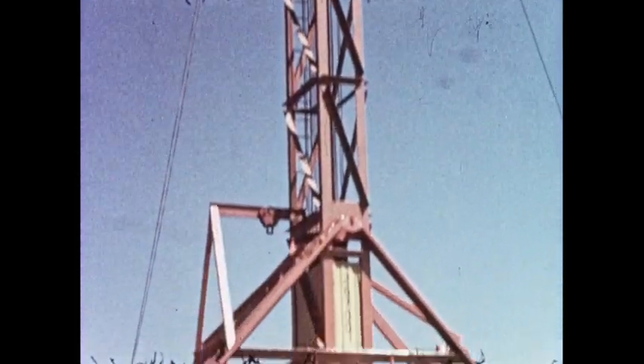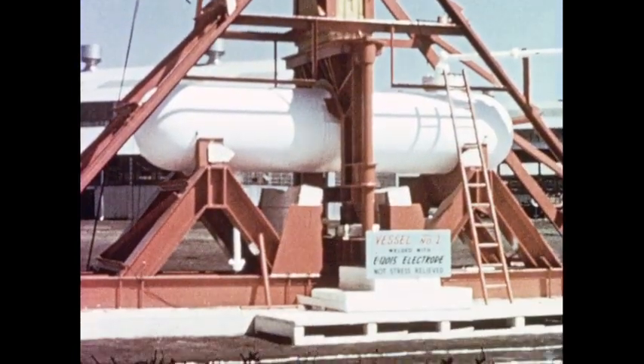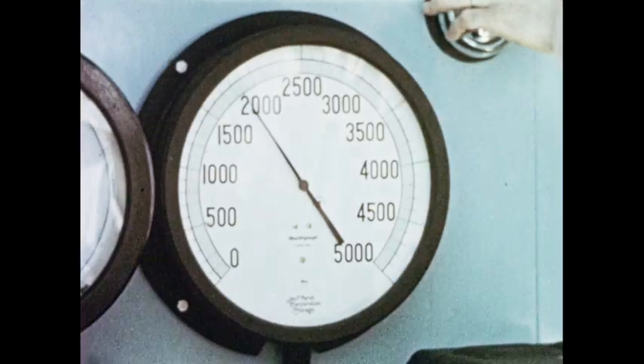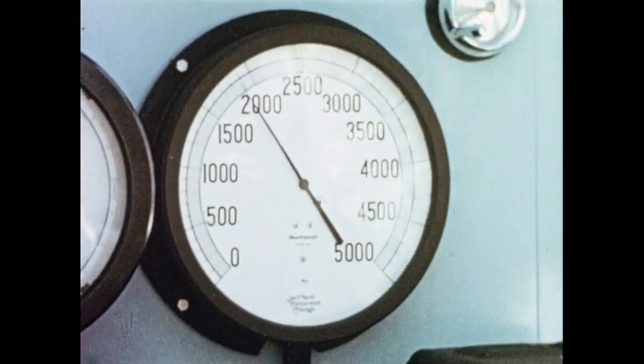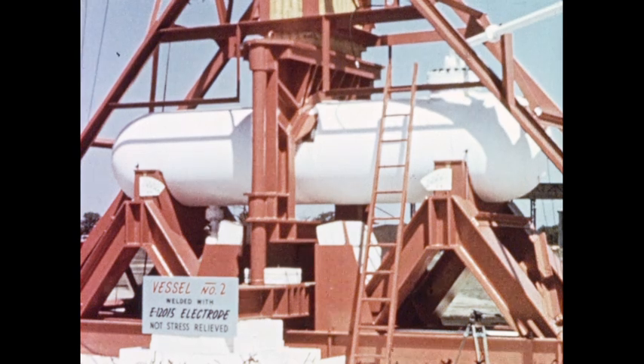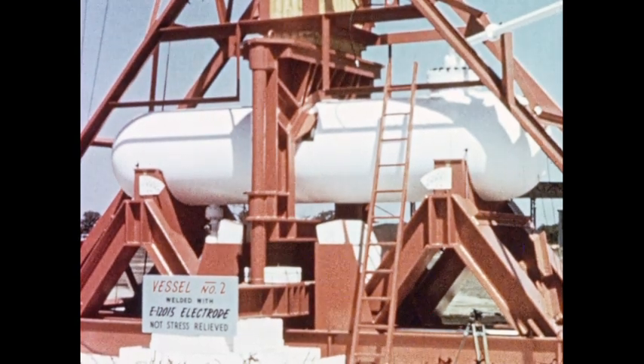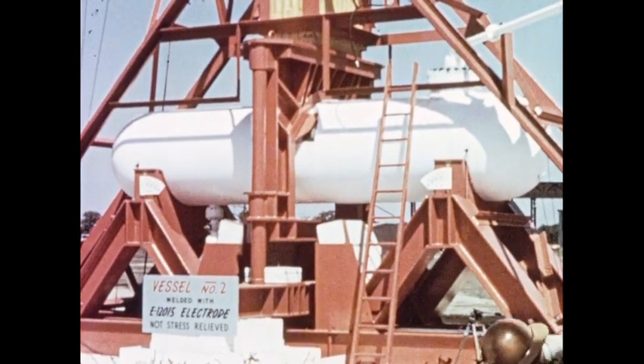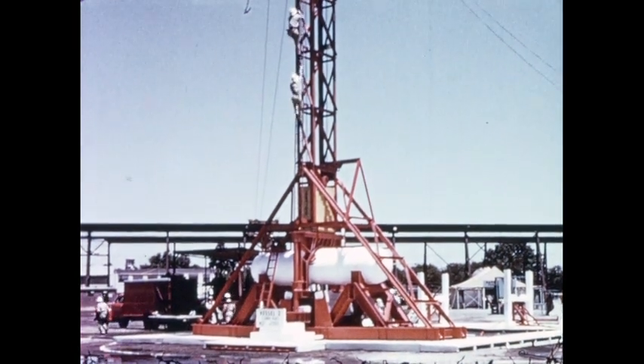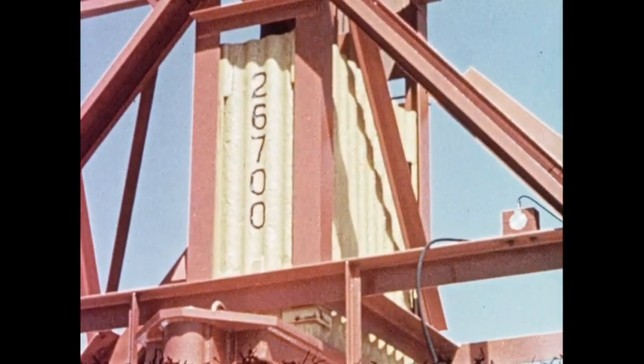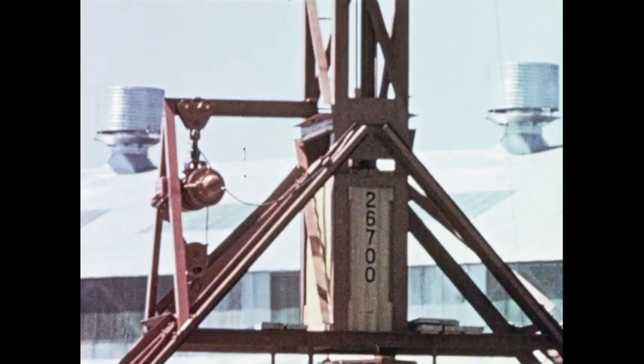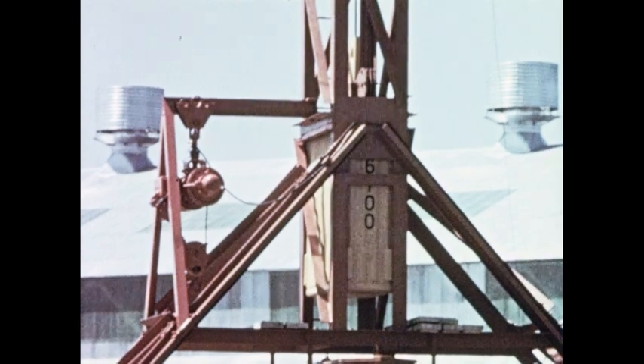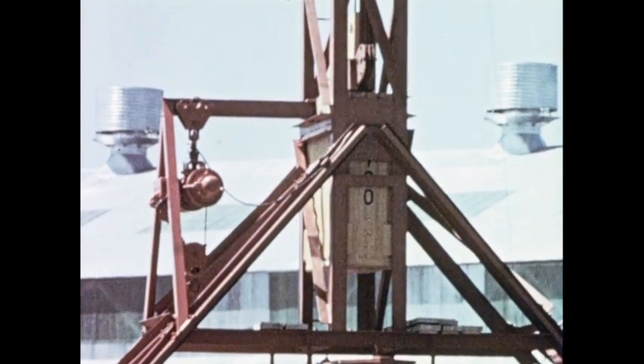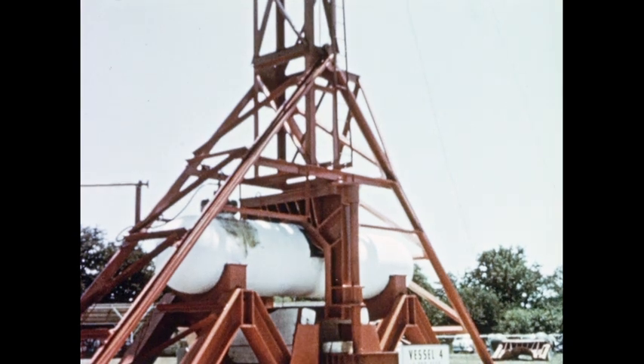The impact test was even more brutal and dynamic. The vessel's temperature was dropped to minus 38 degrees Fahrenheit, and its internal pressure raised to 1,875 psi, the nominal limit for T1. Here certainly were adverse conditions for meeting the colossal hammer blows in store. Suspended in the 150-foot tower was a massive weight, ready to hurtle down with devastating impact. This tub, weighing over 13 tons, was raised to a height of 52 feet for the first drop. A force of almost 1.5 million foot-pounds.